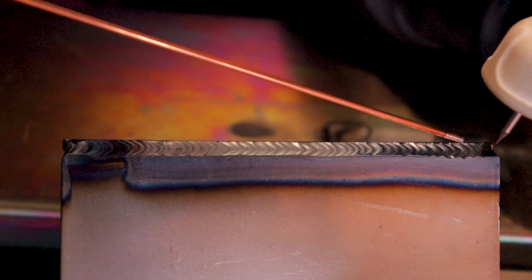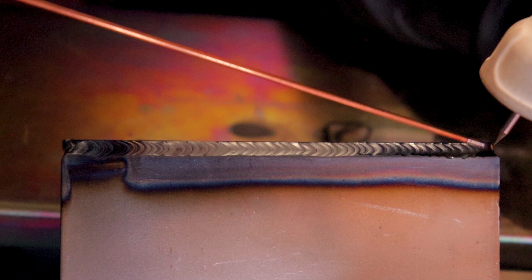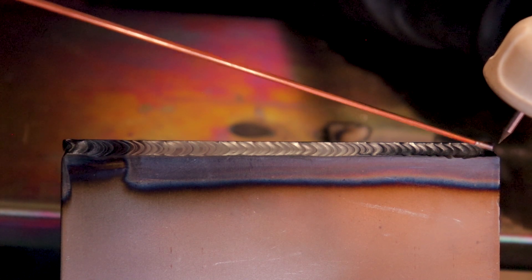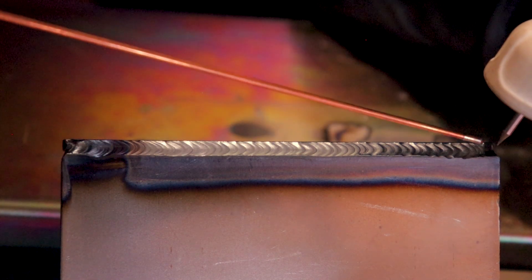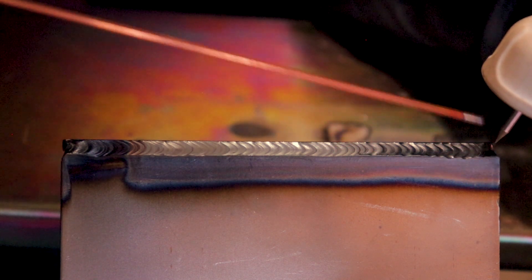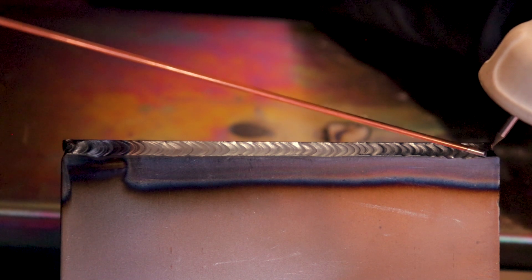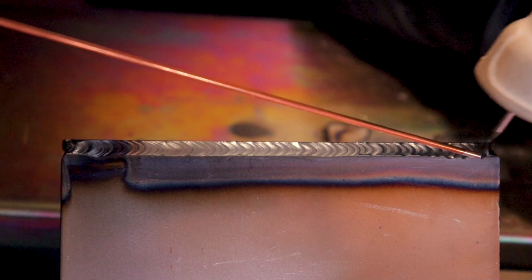And then you're going to be, as you're pushing on that pedal, adding the filler in until it crowns up as high as you'd like. And when you're pushing the pedal down it's not a slow ramp up, it's a quick burst. So once you get your first one going and you feel where it's at with your pedal and how wide it is, you kind of try to remember that with your foot so it's a constant. You're going to the same spot each time.